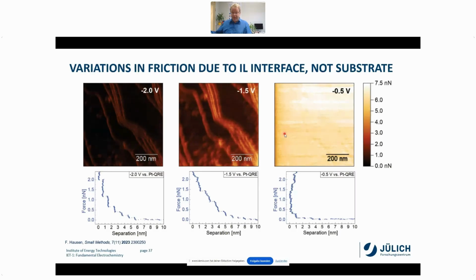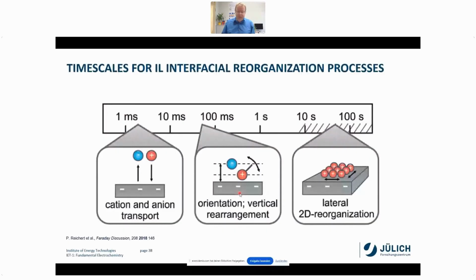So the friction is clearly changing as a function of potential in these ionic liquids, while the substrate remains unchanged. And we see that these ionic liquid layers change drastically at negative potentials. They have a way more ordered structure than at only slightly negative potentials. And now we were interested in what happens if we switch the potential.